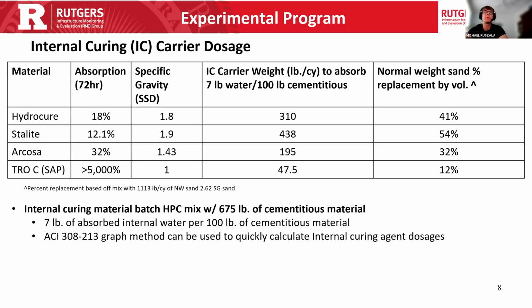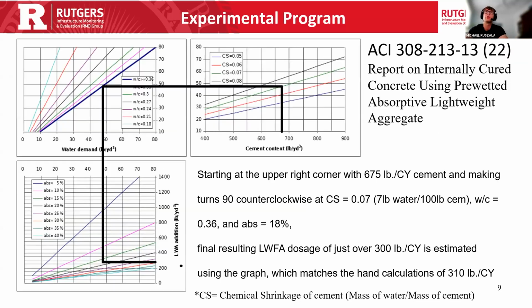There's the ACI 308 213 graph method, which I'll go over here. So it's pretty straightforward. You'll know your base mix, so you have these properties effectively. So you have your cement content, or cementitious content. You have your dosage, typically selected at 7 pounds of water per 100 pounds of cementitious material. So that's the CS. You know your water cement ratio of your base mixture, in this case of 0.36. And then you test the material for whatever its absorption capacity is, and there you have your dosage. So it's an easy way to double check and just ensure that you're properly dosing your material.